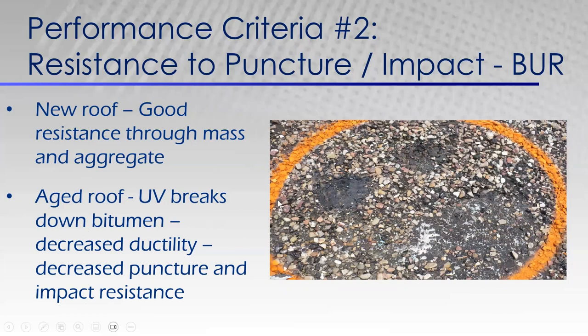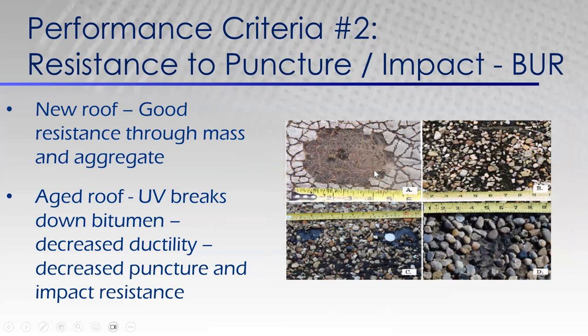You can see here where hailstones have actually hit the roof, and you can see that the granules have been displaced. But what's not so evident is the damage of the impact that is caused on the roof system as a whole. So even as the aggregate was moved apart and it looks like the bitumen is there to protect it, and while it may look like it's okay, with closer examination, let's go to our next slide, you will see how it actually breaks down and creates microfractures.